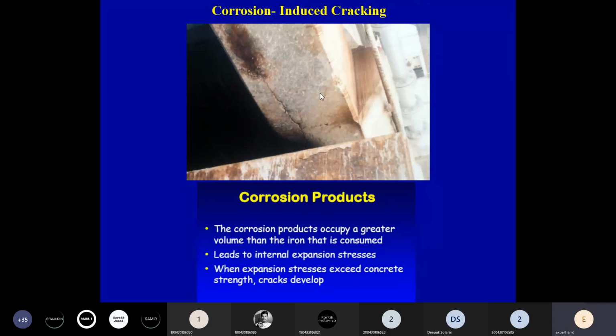Again, I would like to add here that once carbonation happens, it does not necessarily mean that corrosion will happen. For corrosion to happen after carbonation, you need a certain amount of moisture, a certain amount of humidity. So at a humidity level of 50 to 75, carbonation will happen, but corrosion will not happen. Corrosion will start at humidity levels of 95 to 100, where there is moisture and humidity in that range. After your carbonation has reached your rebar level, and your humidity is in the range of 95 and there is an ingress of moisture and water, then the corrosion will start. So we need to understand the complete mechanism, then only we will be able to interpret the data.